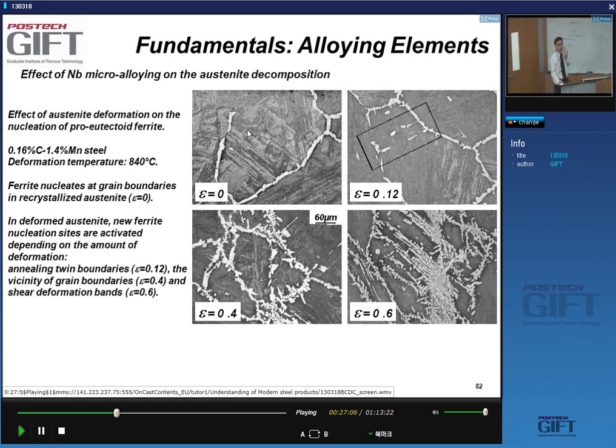Then the only ferrite I see, obviously, will be the one that's formed early on in the transformation, and that is grain boundary nuclei, which have slightly grown. And you can see it around the grain boundary and nothing inside the austenite grain. I deform a little bit, 0.12, and I can already see that there are patches of ferrite, of course, inside